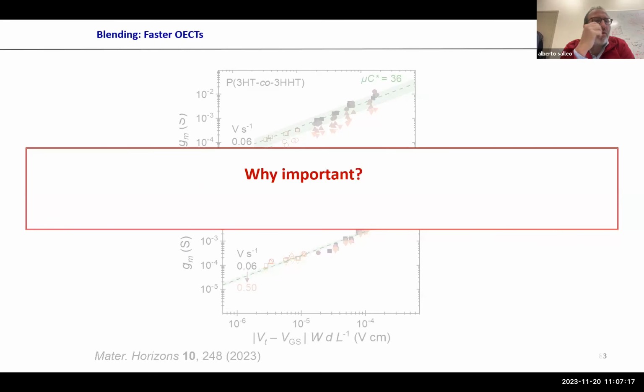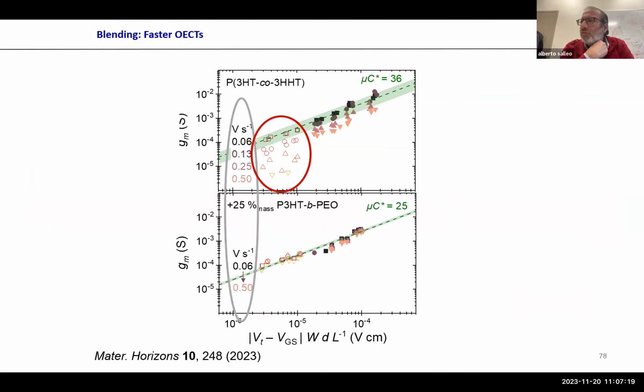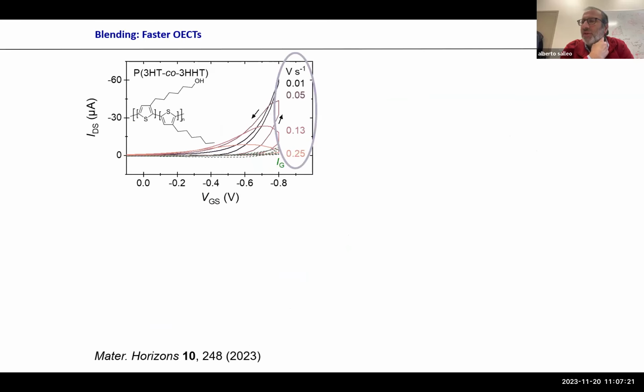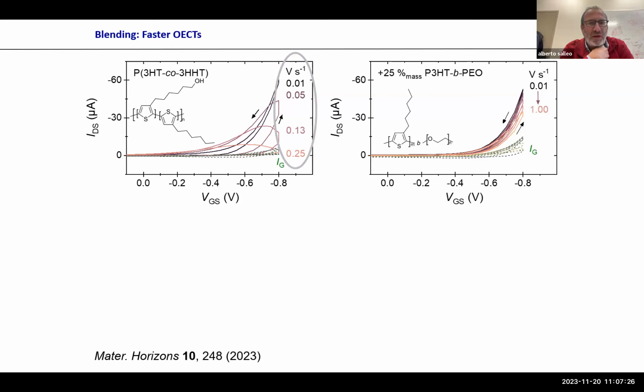I agree, and they would probably do something to the mobility. An analogy is a very nice experiment done in field effect transistors, called the Fröhlich effect or something like that, where depending on the dielectric you got different mobilities, because you're polarizing a dielectric under the charge, and you're carrying not only your polaron in the semiconductor but the polarization in the dielectric with you. So I think that's the direction happening here.